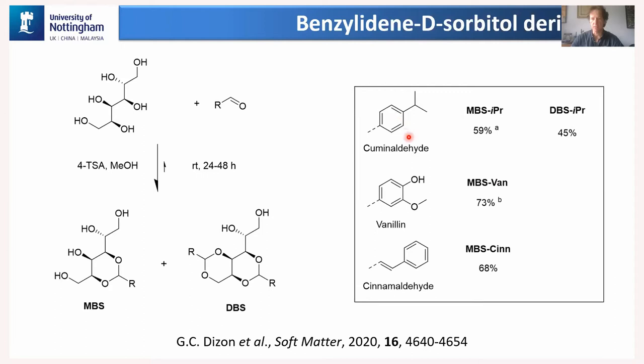Cumin aldehyde is quite nice because you can prepare both the monobenzylidene sorbitol derivative, this one here with all the hydroxyl groups that are still free, and the dibenzylidene sorbitol derivative here, where you've got two of these groups hanging off there. You can do that selectively. One thing I should point out actually is that this chemistry is extremely specific. If you look at all of these hydroxyl groups on the compound here, you think that you might get aldehyde adding across any of these hydroxyl groups.